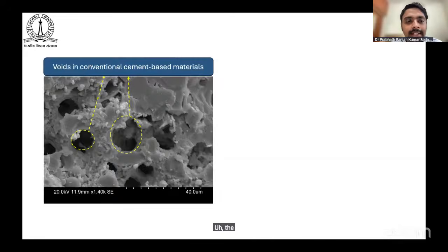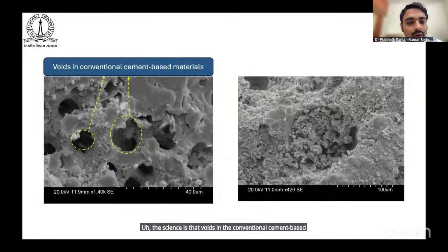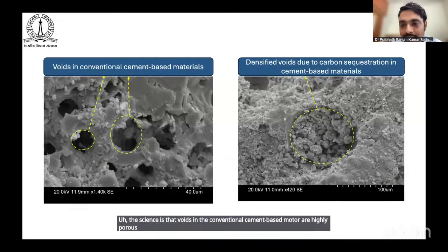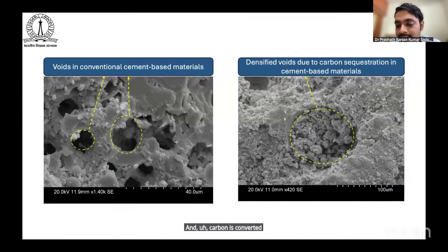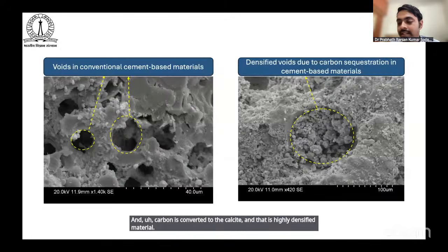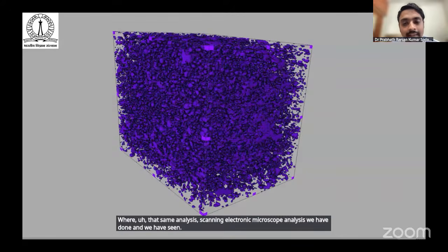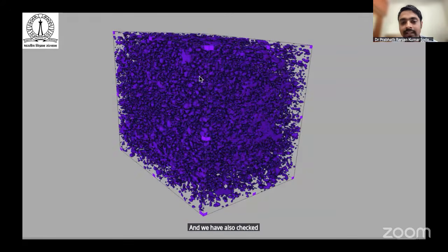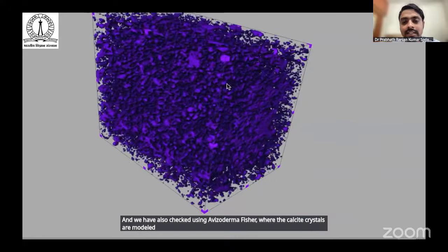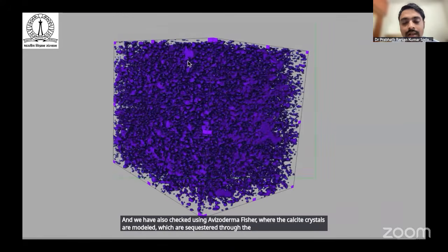The science is that voids in conventional cement-based mortar are highly porous, whereas when you expose them to carbon dioxide, the carbon is converted to calcite, and that is a highly densified material. You can see there is densified concrete. It's an example location where we did SEM analysis, scanning electron microscope analysis. We have also checked using Avizo Thermo Fisher, where the calcite crystals are modeled, which are sequestered through carbonation or carbon dioxide exposure.